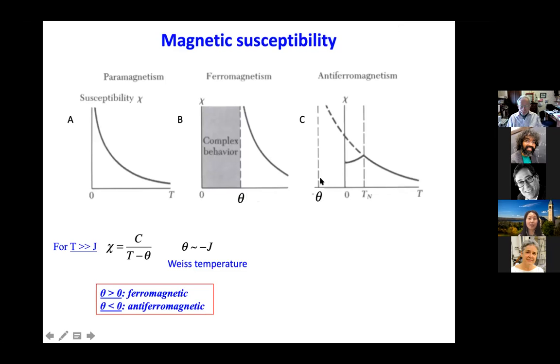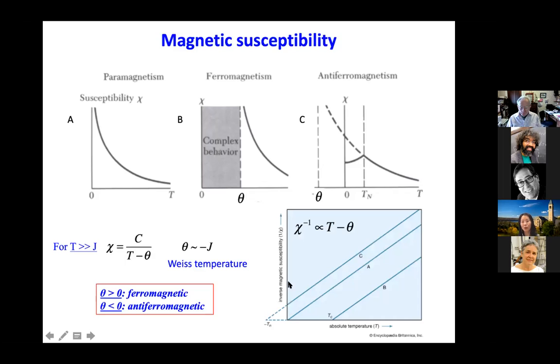And from a textbook, we know that if you can measure the temperature dependence of the susceptibility, you will get an idea of the nature of the magnetic interaction. So for example, if the material is paramagnetic, you cool down your sample, your susceptibility diverges at zero temperature. And if it's ferromagnetic, it diverges at the Curie temperature. And if it's antiferromagnetic, you have to extend the high temperature susceptibility, and you get to a point that looks like it diverges at a negative temperature. So this is a simple picture, and it's the Curie-Weiss law, describing the interaction of localized moments.